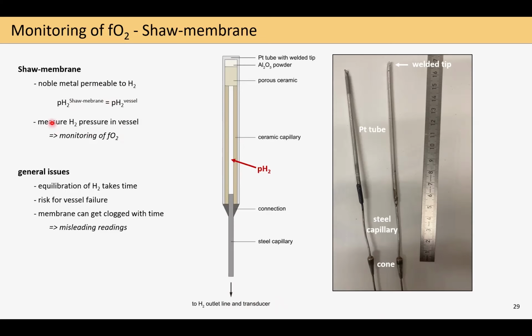Meaning that when we measure this hydrogen pressure, we can directly monitor the fO2 imposed by our vessel on our capsules. However, there are some issues with Shaw membranes. For example, their equilibration in hydrogen partial pressure can take quite a while, and it's very hard to judge at which stage we have reached equilibrium or not.